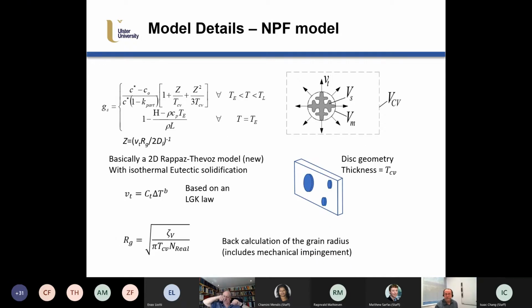Some other details here. We use a Rappaz-Thévoz model. It's essentially Chen-Stefanescu, to be honest, with an isothermal eutectic transformation. We're using the LGK growth law, and a new addition to the model here is that we're trying to represent the radius of growth on average, the average growth radius at any particular point. We do this by a back calculation, and we'll show you some of those results today.